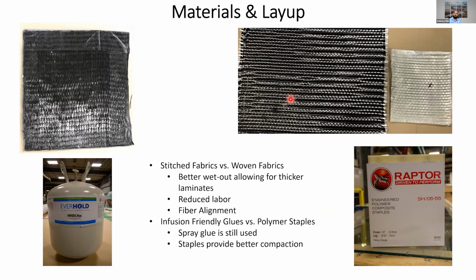Now, the 3D woven fabrics help with a faster wet out, and that allows for thicker laminates to be infused. It also reduces the labor because you can have thicker dry fabrics laid into the mold. And also you can get better fiber alignment as a composite technician is handling this material. The stitch fabric, sometimes the stitches are a bit loose and the fabric doesn't align as easily as you'd want it. So we've used woven fabrics for both carbon and some of our glass layers.